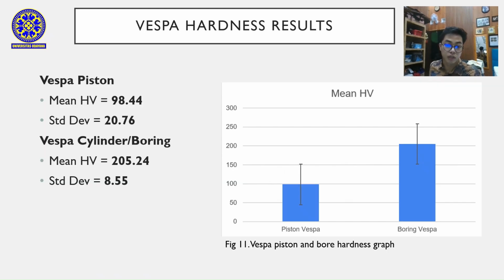For the Vespa component, the piston had an average hardness of 98.44 HV, with a standard deviation of 20.76, indicating a noticeable variability across the test points. Meanwhile, the Vespa boring exhibited a much higher hardness of 205.24, with a low standard deviation of only 8.55, showing a much more uniform material condition. This difference is consistent with the functional requirements of the two components.